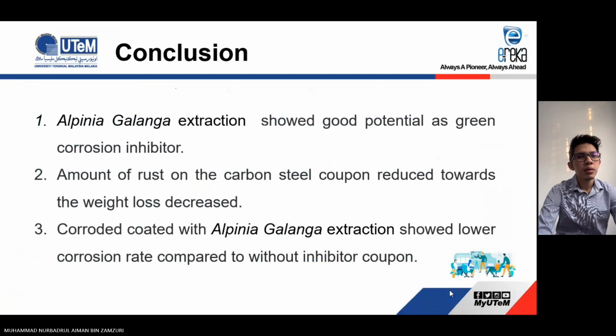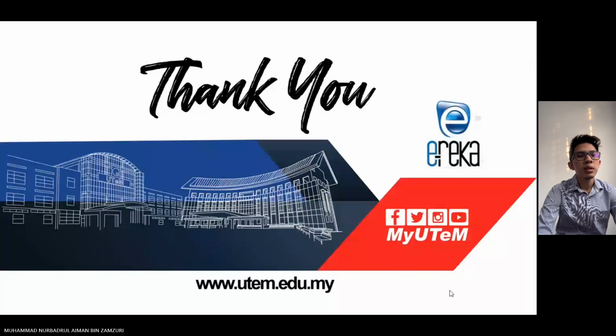And then, as the conclusion of this bahan perencat hijau presentation, we can conclude that Alpinia galanga extraction showed good potential as green corrosion inhibitor. Moreover, the amount of rust on the carbon steel coupon reduced towards the weight loss decrease. Then, the corroded coupon coated with Alpinia galanga extraction showed lower corrosion rate compared to the without inhibitor coupon. That's all from us.